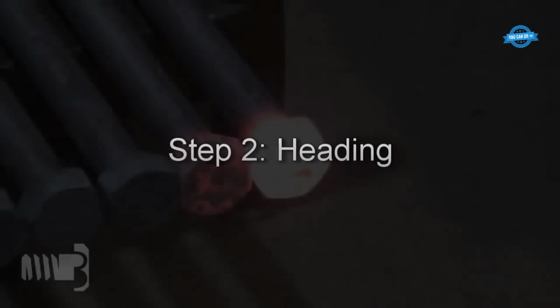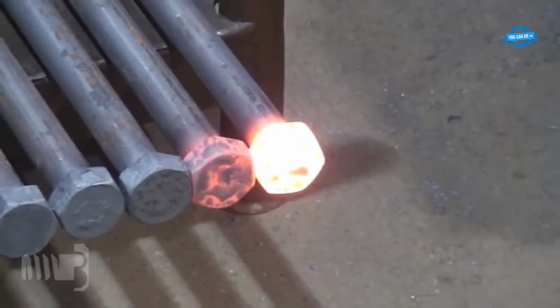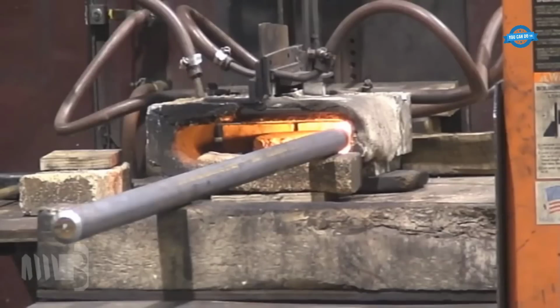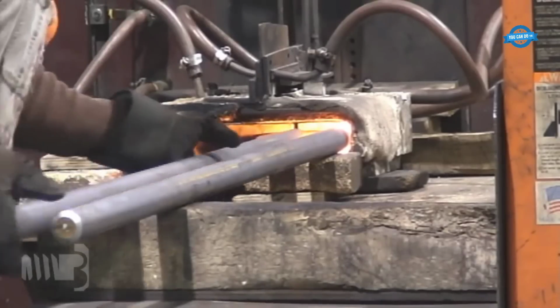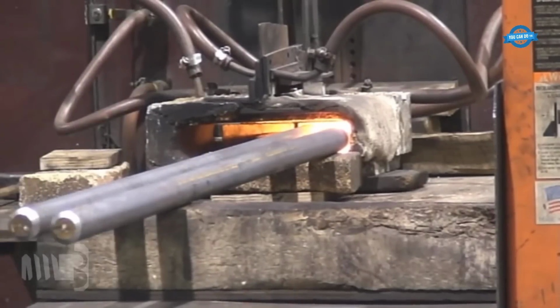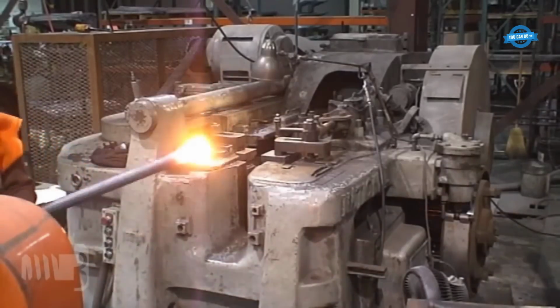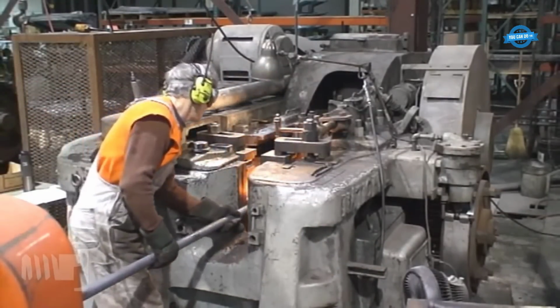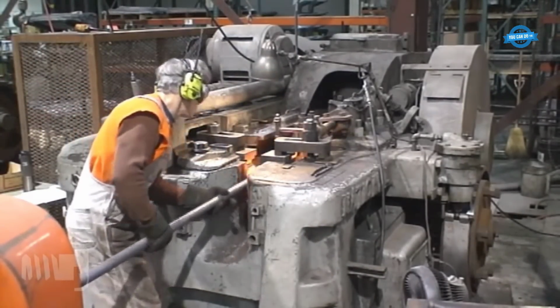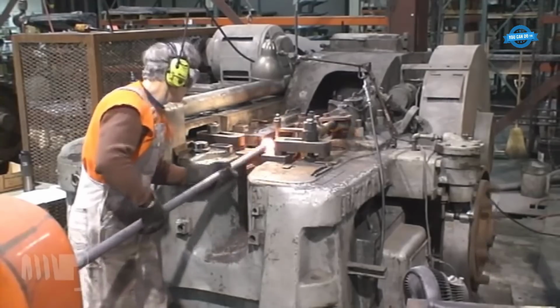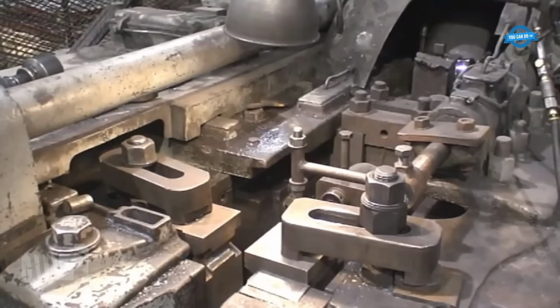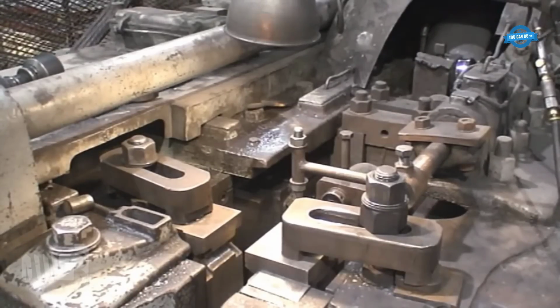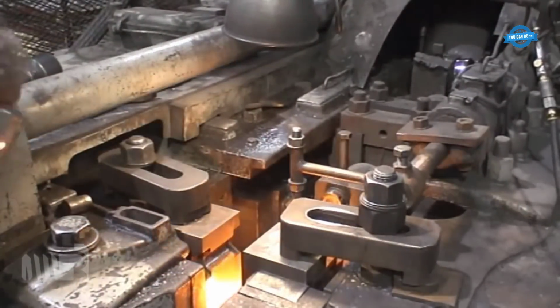Heading. The hex head is hot forged onto one end of the steel rod using an induction heating coil that heats the end of the rod to around 2000 degrees Fahrenheit. The National upsetter is then used to forge the heated end of the rod into a hex-shaped head. Gripper blocks clamp the round bar securely in place, while a plunger or die compresses the heated end of the rod, reshaping it into the hex head configuration. The manufacturer's logo and grade symbol are then stamped onto the head as required.